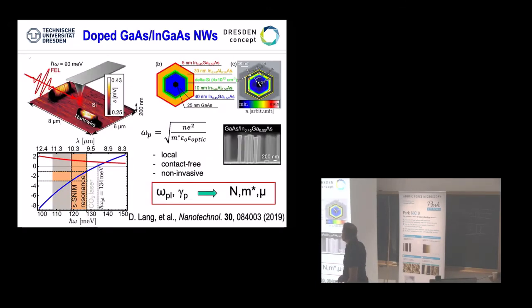So we see that we can really get n here, actually, the number density. We took a second example, which is actually shown here. This is a linear, one-dimensional system. These are gallium arsenide sticks, as you see here. And we've been really cutting them down, laying them on the surface, and doing exactly the same experiment with the s-SNOM like before. Now we have both. We have phonons and plasmons in this. So we need to do the full fit, not only the plasmons.